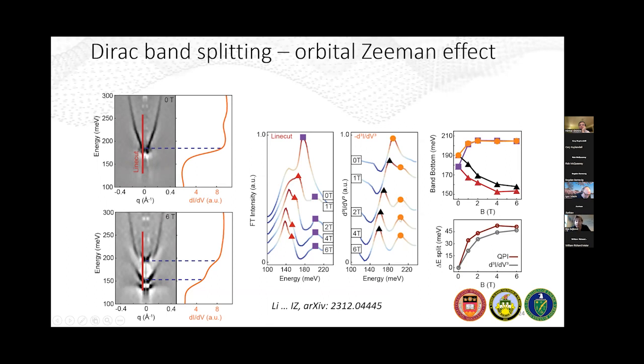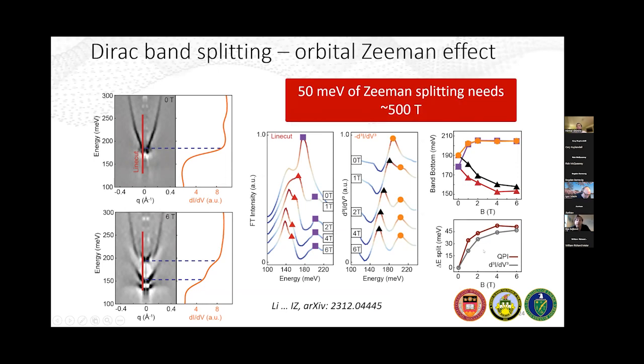We can quantify that both for the dI/dV spectrum and for the splitting of this momentum space Dirac dispersion that you see here on the left. In both cases, this is essentially the summary. So the splitting from 0 Tesla to these higher fields is from, I guess, 0 millivolts to about 50 millivolts. So the splitting is on the order of 50 millielectronvolts, which is enormous. And we can directly see that from the momentum resolution our STM has, that it relates directly to the splitting of the Dirac dispersion. By a conventional spin g-factor, one would need several hundreds of Tesla to achieve this.